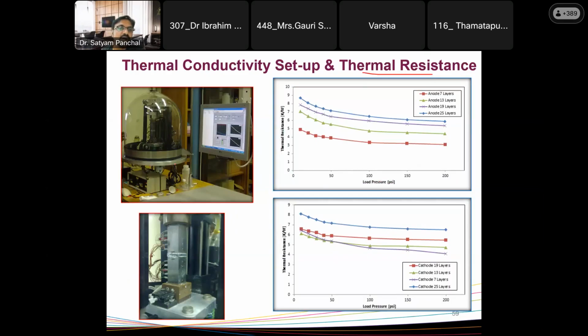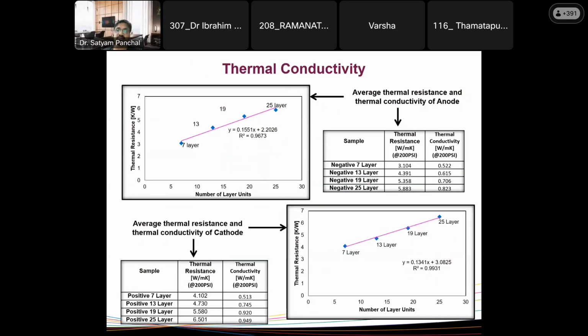So here you can see this thermal conductivity setup, and here you can see the RTD, the resistance part. Here you can see those load distribution thermocouples, and a 1 inch by 1 inch sample was placed over here, and at different layers, as I said, 7, 13, 19, and 25 layers, at different load pressures, thermal resistance was measured, which you can see over here. This type of data is helpful to thermal modelers also. And then, as I said, thermal conductivity was measured for 7 layer, 13 layer, 19, and then 25 layer with a linear fit equation.